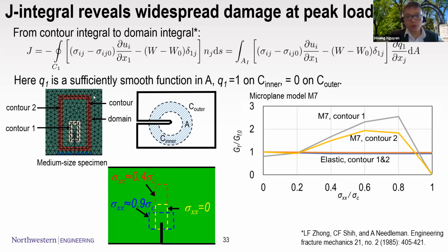And I use two contours here, and you can see from the relation and also from the magnitude that the increasing contour 2 agrees better with whatever we measure from the FE. Contour 1 is too close to the crack, and one hypothesis of the J integral is that it should not cross any unloading area or unloading volume. Hence, contour 1 still gives an unconverged value of the J integral. So that's something we should keep in mind.